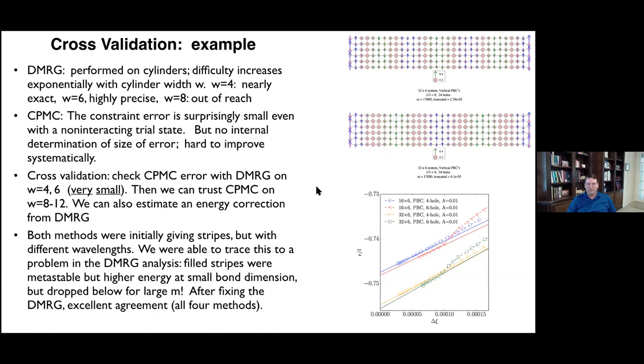We eventually resolved this to an issue with the DMRG convergence, and that's shown down here. So what we think is eventually the low energy state starts with small bond dimension as a higher energy state. And then there's a crossing over. But it's a very subtle crossing over, because as I go down these lines, this is the final sweep. And the final sweep, the higher energy one is still at a lower energy than the final sweep here. So unless you do this careful extrapolation to see where they're going, you would say that the blue is better.